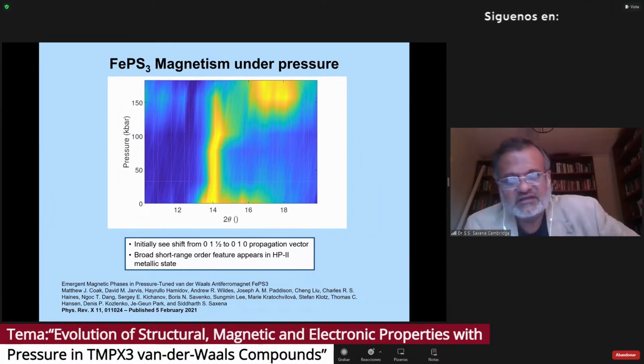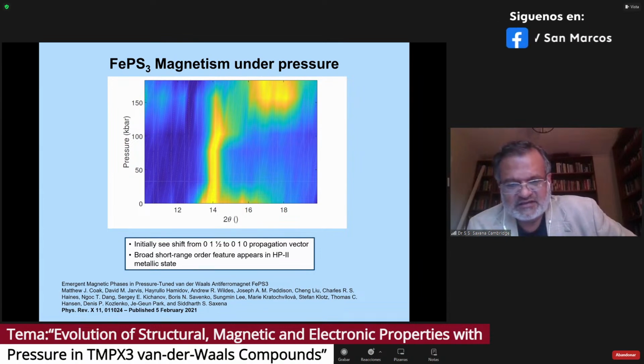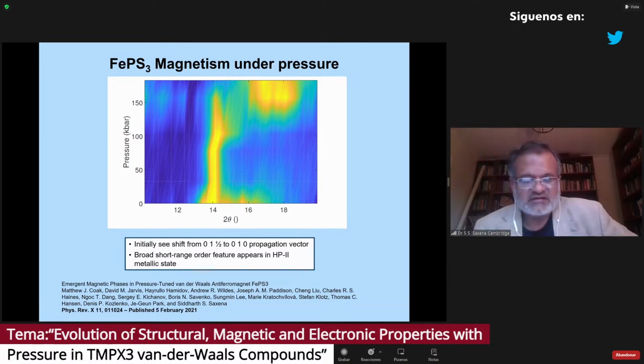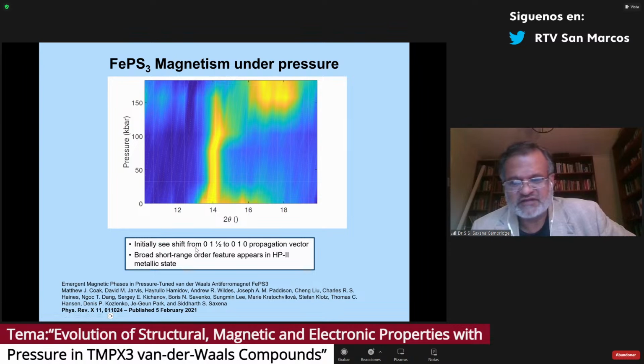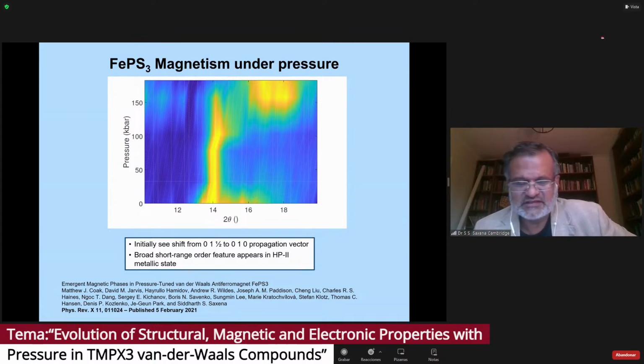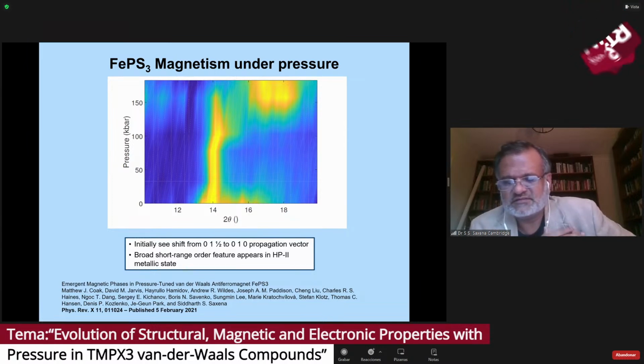And so we conducted, at least in our kind of correlated world, perhaps the highest pressure neutron experiment, at about 180 kilobars, and we were able to follow the shift of the magnetic propagation vectors from (0, 1, 1/2) to (0, 1, 0). Again, this is a talk by itself to go into the details of this data, but it's published in Physical Review X in 2021. It shows how the system evolves from a magnetic insulator to a magnetic metal.